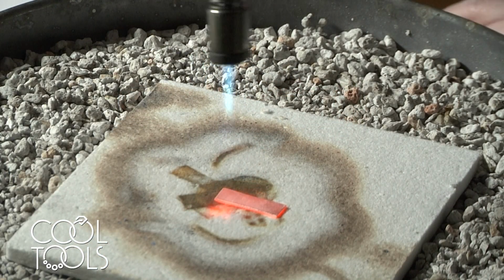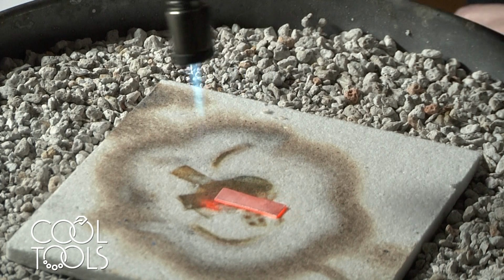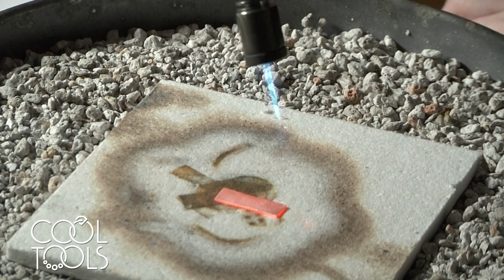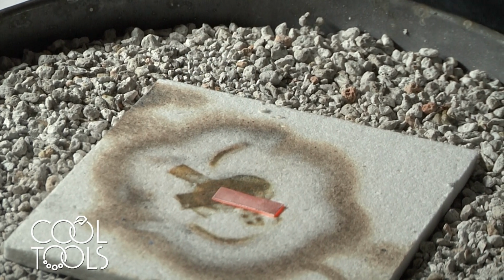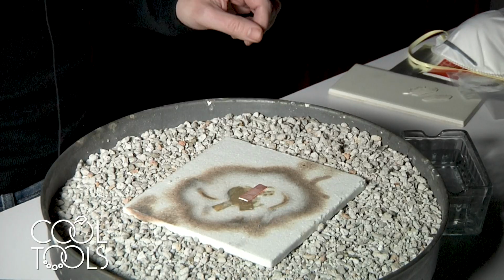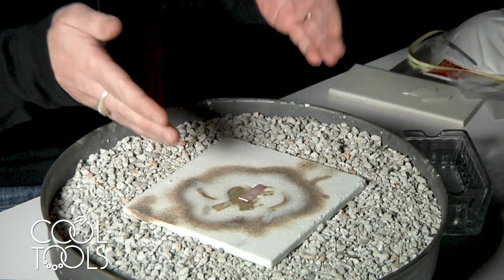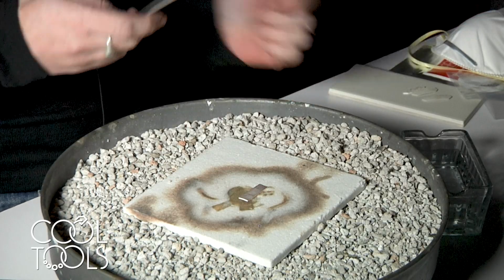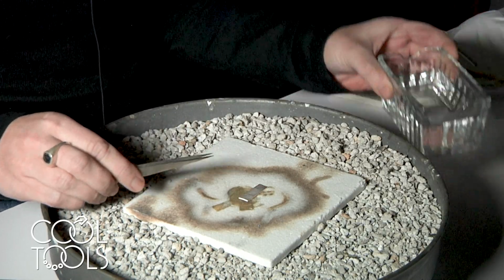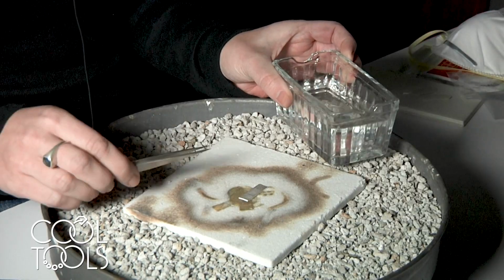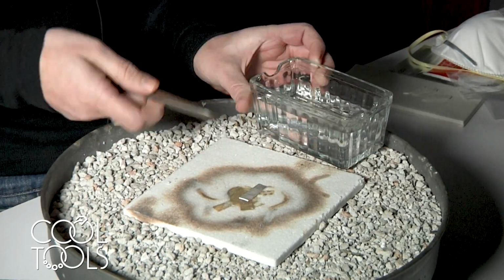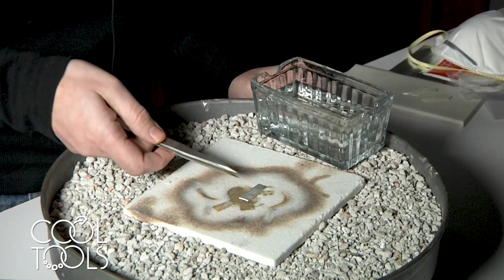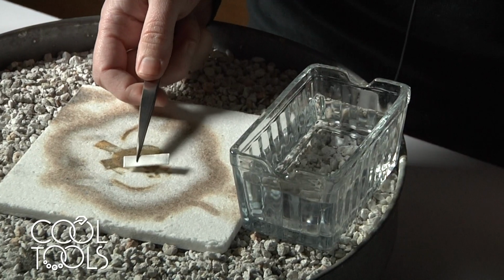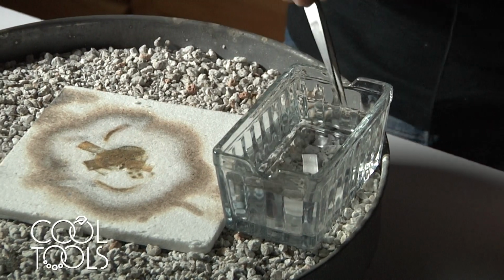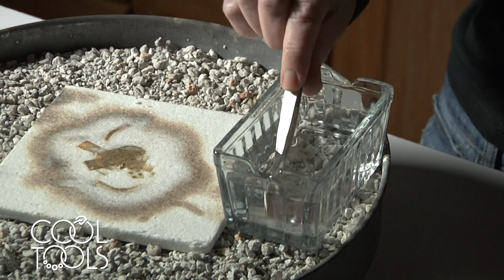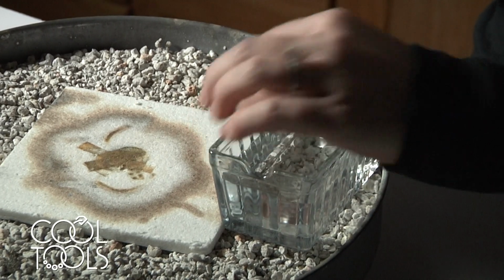So I've had my flame on my piece for about 4 minutes, and that is sufficient for a piece this size. So at this point, I'm taking my flame off. And then, since I don't have any gemstones or anything that's going to suffer from thermal shock here, I can quench this piece. And I'm bringing up my water to my fireproof environment instead of bringing my piece over and across a non-fire safe surface. And I'm just dropping it in. And that's a quench. It rapidly cools your metal so that you can handle it.